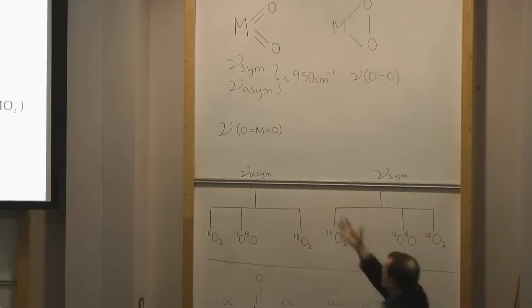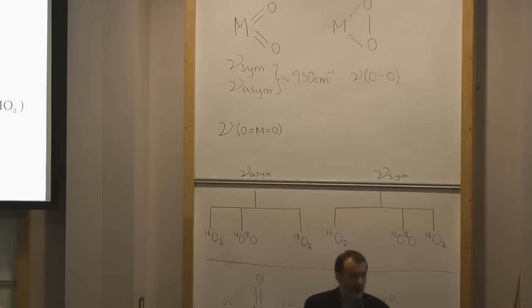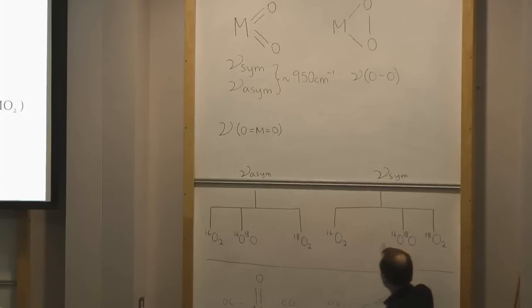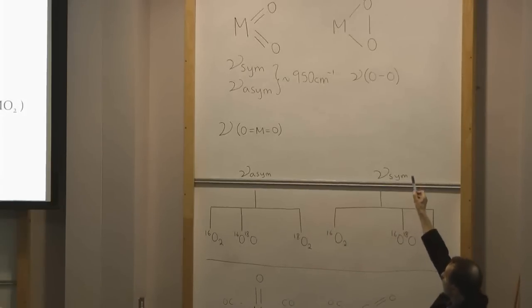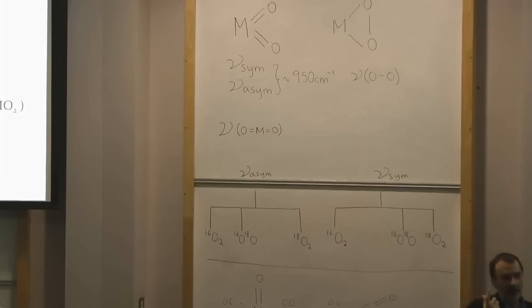In C2V symmetry, which is what we have there, they don't mix with each other for the pure isotopes, but for the mixed isotopes, the symmetry is lowered, and the two vibrations mix, and they push each other apart. So if you get the three isotopes, you see an asymmetrical triplet of bands for the asymmetric and the symmetric stretch. These two bands push each other apart, whereas if you have the peroxo unit, where the oxygen-oxygen bond is intact, there's no reason for that to happen, so you get a symmetrical distribution of bands, and that's a classical way of trying to distinguish those two units by vibrational spectroscopy.